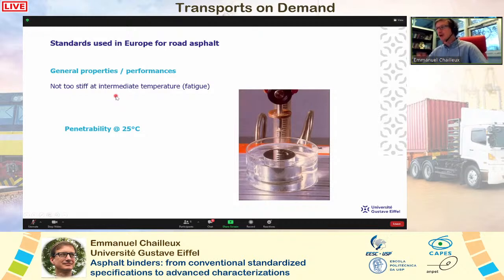At intermediate temperature, in fact, we measure the penetrability at 25 degrees, and this well-known penetrability test is used to define the grade of bitumen. The principle of this test is to let a needle go into a binder at 25 degrees during 5 seconds, and we measure the depth of the needle.